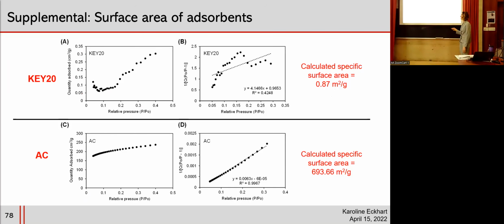All right, so we can see that with activated charcoal, this is what it's supposed to look like. We have an increased amount of adsorbed gas with the increase of relative pressure in the chamber. And this can be used to quantify the surface area, which was about 693 meters squared per gram for activated charcoal. And when we tried the same analysis with Key 20, we got a terrible BET fit. And we think this is because the keys have such a low surface area that it's actually below the limit of detection for the BET. We would probably need to use about 10 times more material in order to get a valid surface area measurement. But I still think this data communicates that the keys have much, much less surface area than activated charcoal, just because using the same amount of material, we were well above the sensitivity of the instrument with activated charcoal and not even close with the keys.